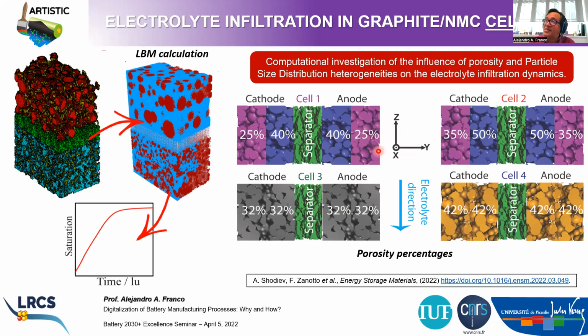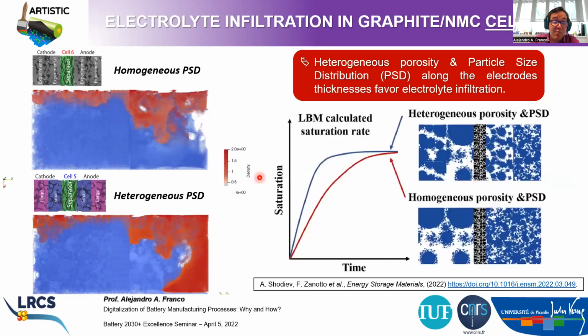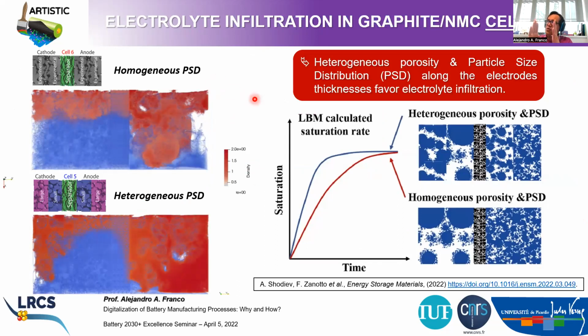But you can also do the same with the particle size distribution. You can imagine, for example, on this side particles which are smaller, and here particles which are larger, and the same for the cathode. Here you see an example for this second case, where you study the influence of this distribution of particle sizes along the electrode thickness. Basically, you have a bilayer structure, with smaller particles on one side and bigger on the other side, and then you compare that with a homogeneous particle size distribution in the full volume of the electrode.